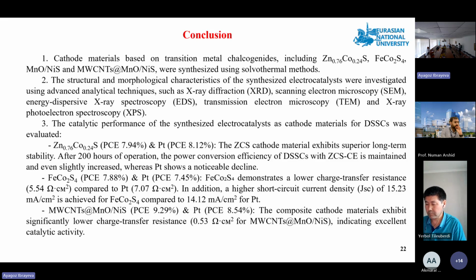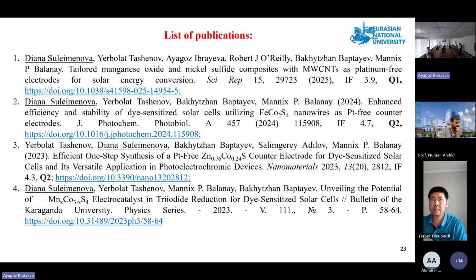Ternary composites of manganese oxide and nickel sulfide with multiwalled carbon nanotubes show high efficiency, 9.29%, versus platinum 8.54%. The composite cathode materials exhibit significantly low charge transfer resistance, 0.53 ohms square centimeters for the ternary composite, indicating excellent catalytic activity. Overall, these cathode materials promise a low cost and efficient alternative to platinum counter electrodes in dye sensitized solar cells.